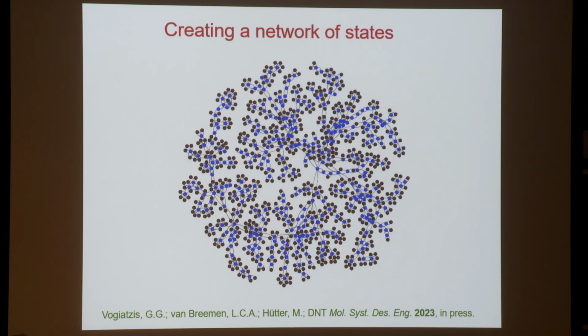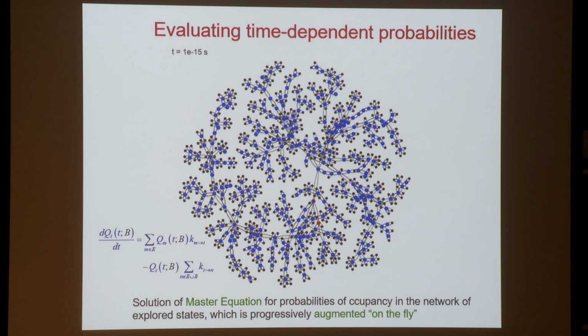So in the end, one has this very rich connectivity among basins, which is represented graphically here. Having this set of states, one can try to solve the master equations for the probability of occupancy of these states. Assume that we start with the system in a given state, for example this red point, and we want to watch the system diffuse out into the rest of its state space. This is the master equation. It tells us that for each of these states, the probability of occupancy changes with time as a result of influx of probability from other states, this term, and efflux of probability into other states. And for the boundary states, the black dots here, we use absorbing boundary conditions.